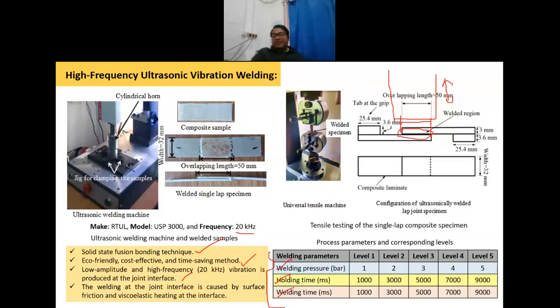Holding time, higher is the better. You can see here 9000 millisecond, which is the maximum here, gives me the maximum joint strength, because holding time is the time you are giving for the consolidation, for the solidification of the melted polymer. That means you are keeping the specimen under pressure for a longer period of time, so it allows the specimen better joining.